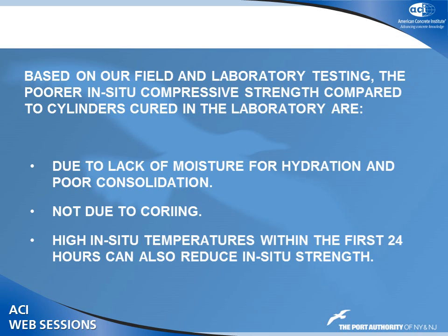We don't think there's much due to coring. Again, we're talking about high-strength concrete. We don't think that much of the reduction in strength is due to coring. We think that most of it is due to this here, and again, temperature. For high-strength concrete, if it's mass concrete, certainly if the temperature shoots through the sky in the first 24 hours, you're going to kill the strength.